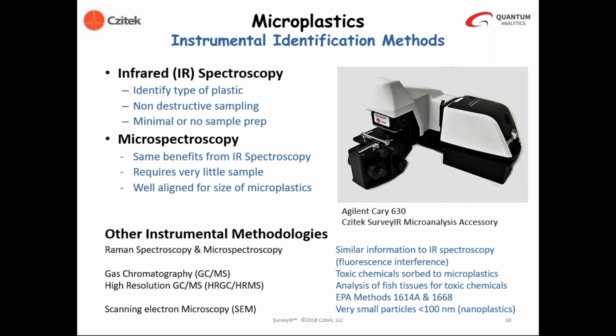Infrared spectroscopy is non-destructive, so we are able to identify materials and analyze them via other techniques if we're able to locate them after the analysis. Microspectroscopy offers the same benefits as infrared spectroscopy, but allows us to identify these samples on a much smaller size and mass scale. Based on our work, infrared microspectroscopy is well aligned for the size of most microplastics that we've encountered in the environmental samples that we've come in contact with.